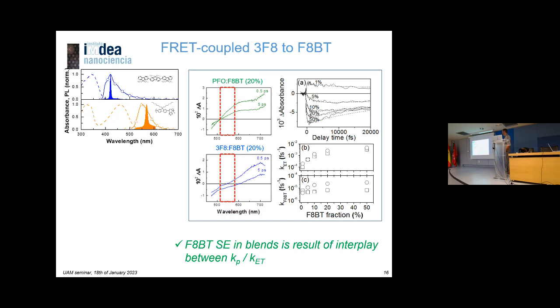You can fix the detection here and monitor the kinetics. These are taken for different concentrations of F8BT in the trimer. What you see is that you always get an initial positive signal, meaning excited state absorption, which is very quickly depleted by stimulated emission.